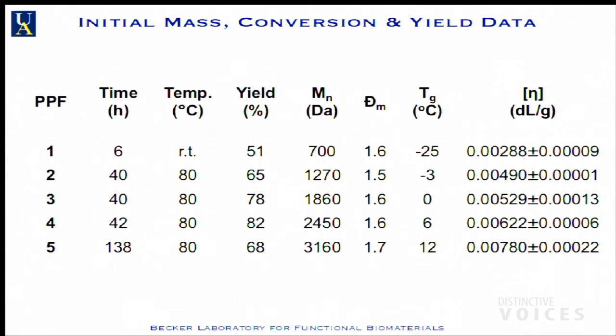And the glass transition property, if you skip all this stuff and look at molecular mass, this is 700 Daltons, 3,000 Daltons, above 4,000 it's a solid. But you can see the Tg here is sub-room temperature, this is -25 to 12 degrees Celsius. More importantly, the viscosity properties. The optimal viscosity here is about 0.005 deciliters per gram intrinsic viscosity. That means it's about the consistency of honey. And you can drop it. You can go to high molecular weight if you heat it and drop it.